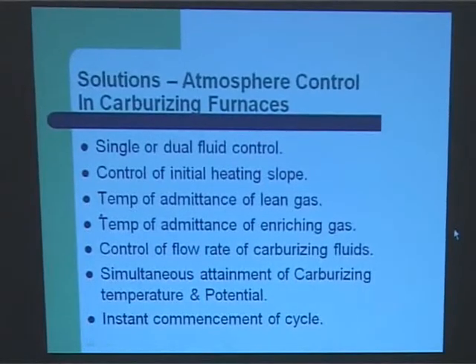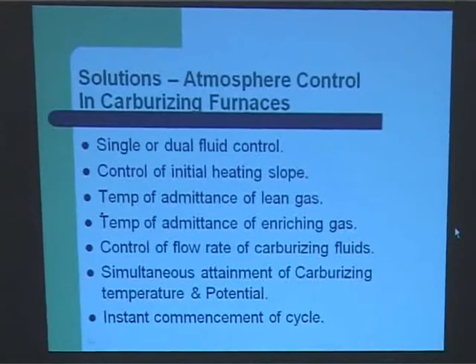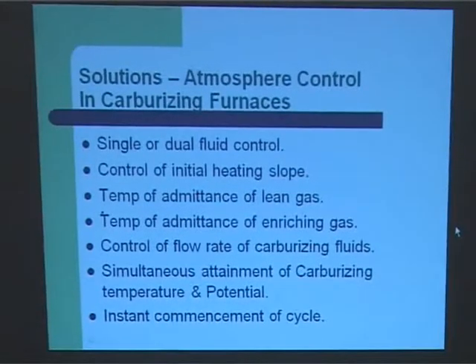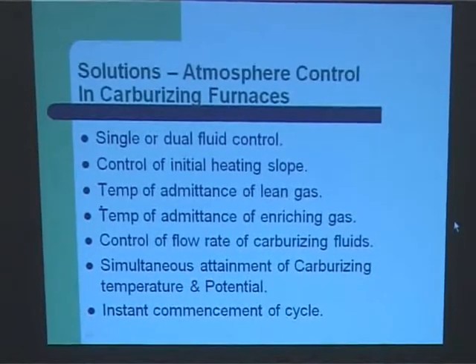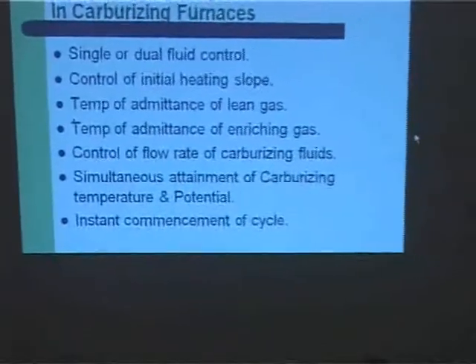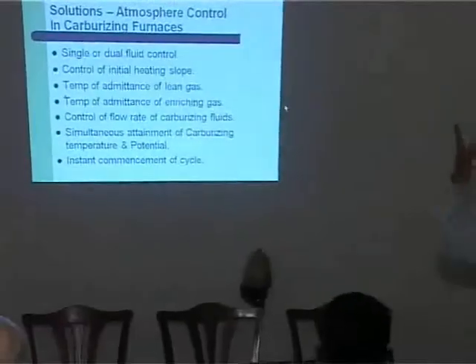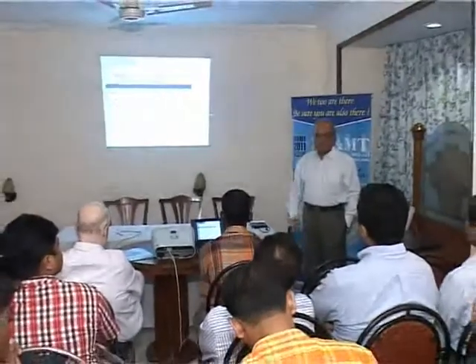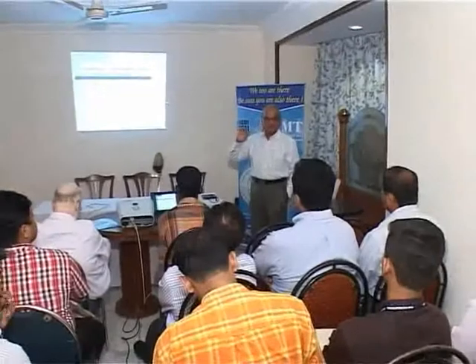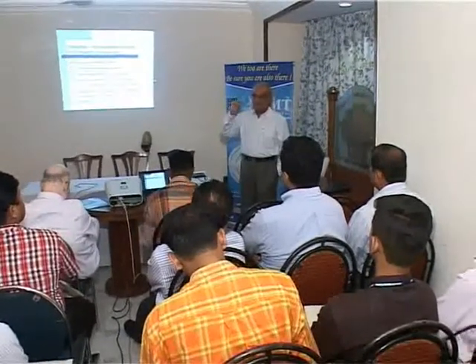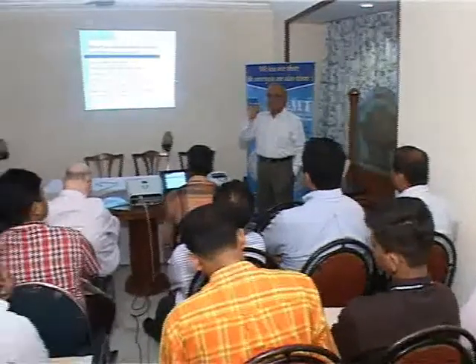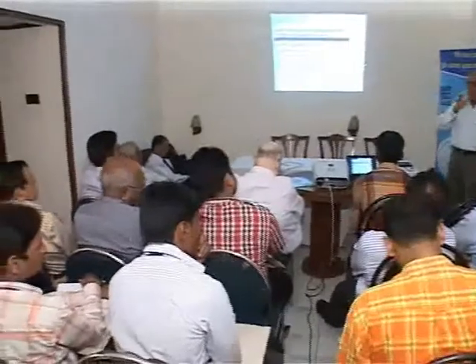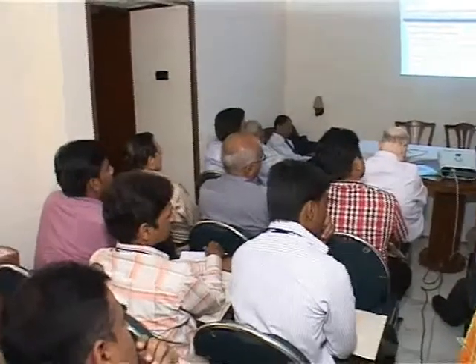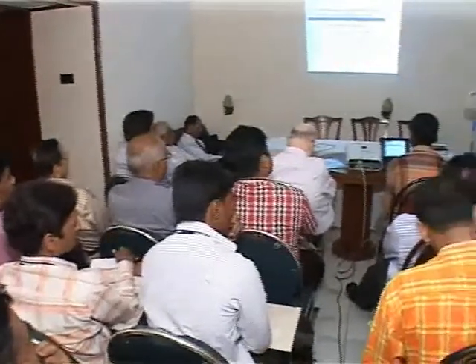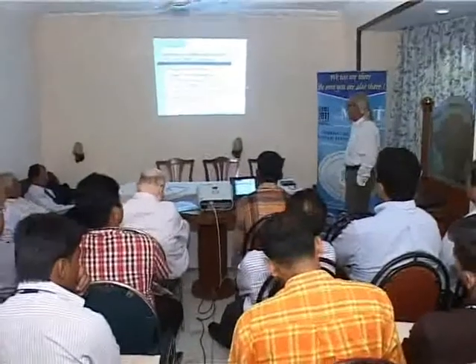These are mostly operating parameters which I am sure all of you know. The third bullet is what I was talking about, temperature of admittance of lean gas. If you start admitting your gas there, maybe acetone or LPG, whatever you are using, at a lower temperature, in small quantity. I am not asking you to consume gallons of it, small quantity. The basic idea is the entire furnace atmosphere becomes reducing, so that there is no loss of carbon from the job. And therefore, when it comes to the ultimate carburizing temperature, the additional boost or dosage of carbon you require is very, very nominal. And therefore, you are able to achieve your case depth and your case carbon in a much shorter time. Instead of say a 5-hour cycle, you may be able to achieve it in 4 hours or 4.5 hours. Next.